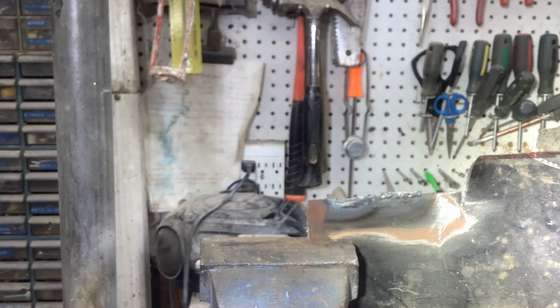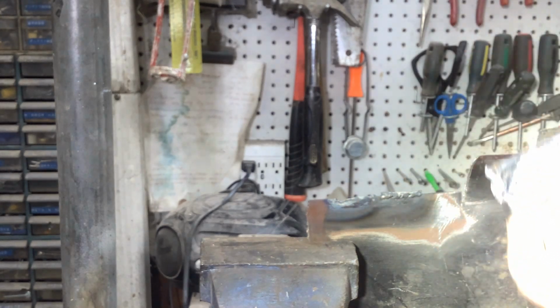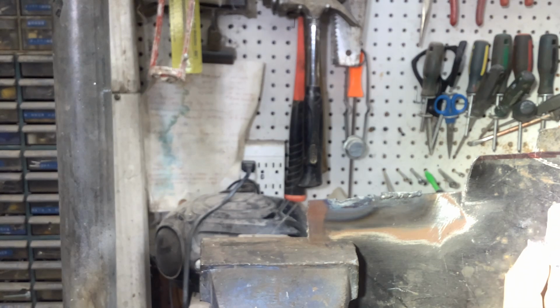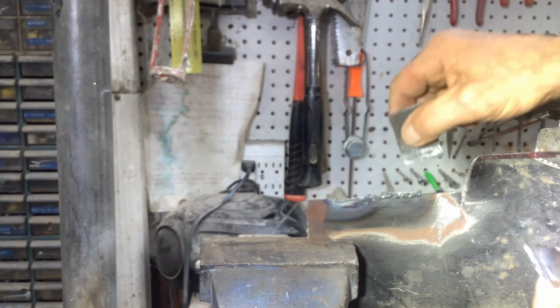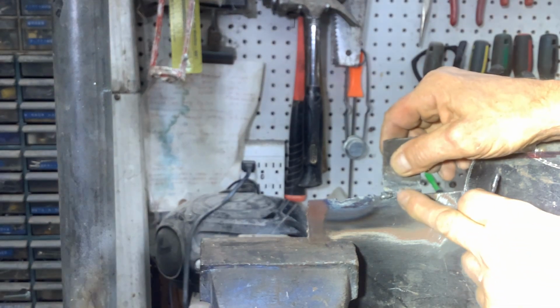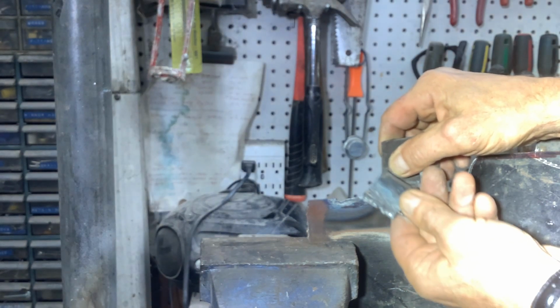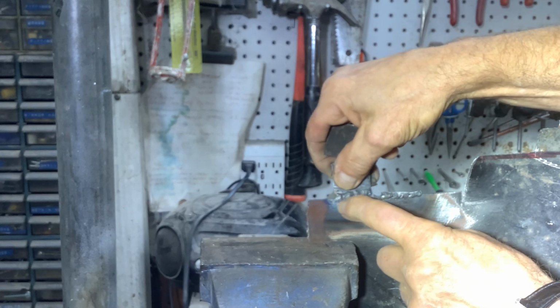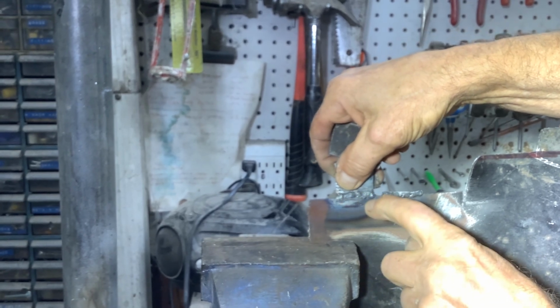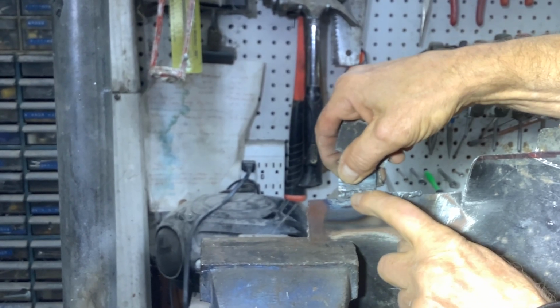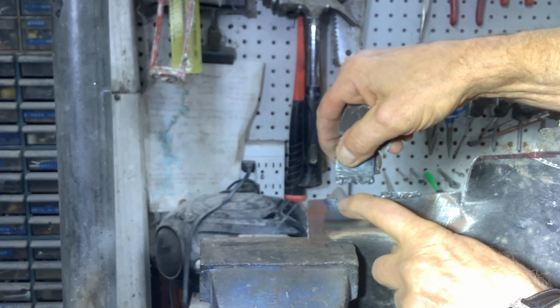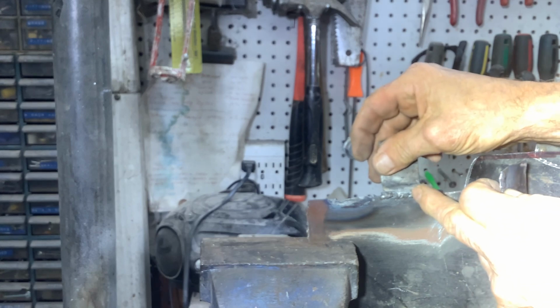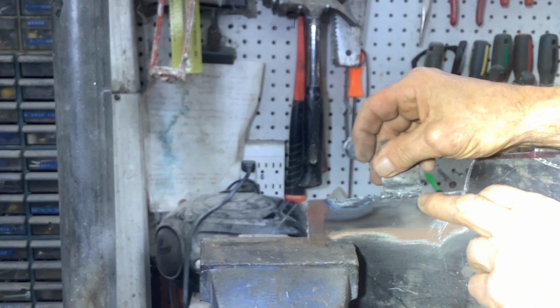Now the weld is broken, but it's not the weld that broke down the center. If you look very carefully, it broke more on the weld here. And here, the metal broke beside the weld. The weld itself did not fail. It's the metal beside the weld. Whereas on this one here, the weld sort of cracked down the middle more.